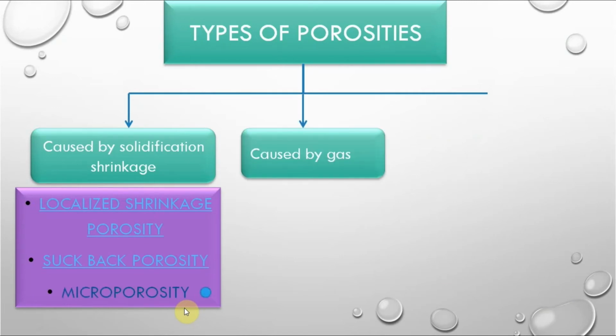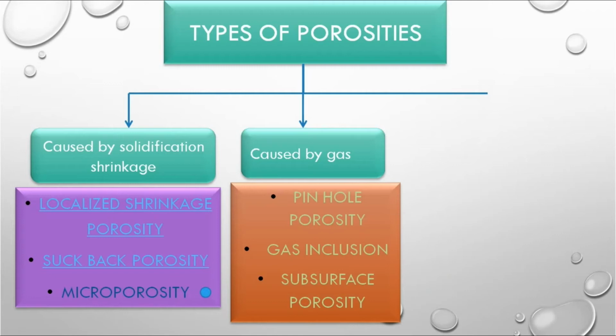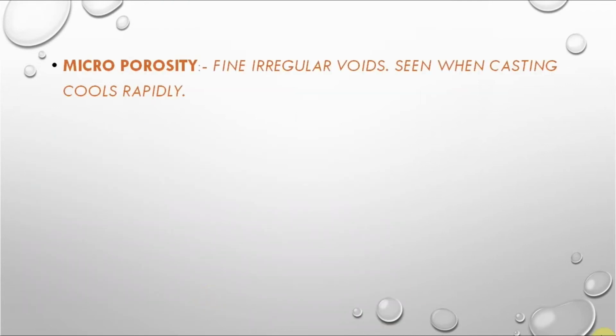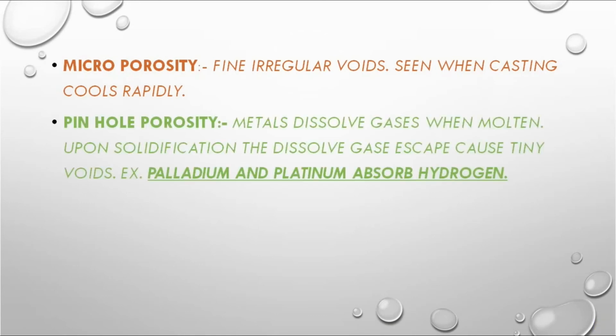Porosity caused by gas are pinhole porosity, gas inclusion and subsurface porosity. In solidification shrinkage, porosity is irregular, while in gas inclusion it is spherical. Microporosity is fine irregular void when casting is cooled rapidly. Pinhole porosity, as some metal dissolve gas when molten and release them upon solidification, resulting in tiny voids. Example is platinum and palladium absorb hydrogen and copper and silver absorb oxygen.